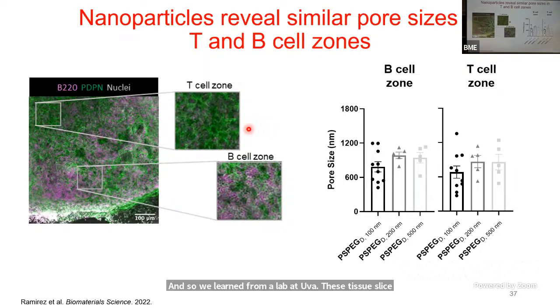So average about 30. But when we did this with our nanoparticle systems, we actually found that when you have cells present, so a complete tissue, not just the extracellular matrix, the pore size is closer to somewhere between 600 nanometers and about a micron in size. And that, again, doesn't matter whether you're in the B cell zone or the T cell zone.